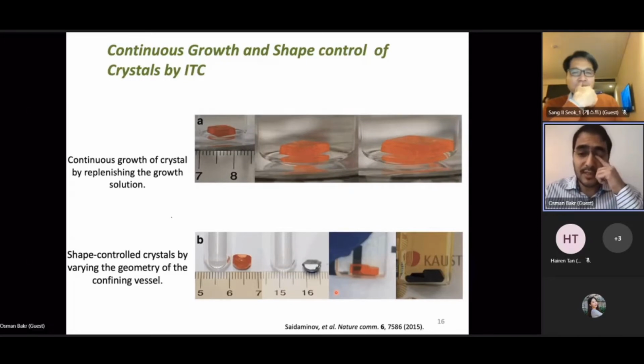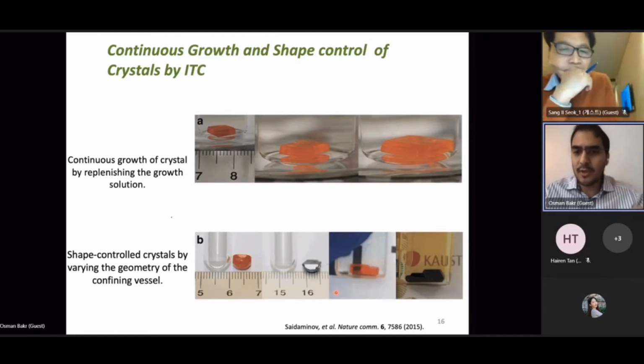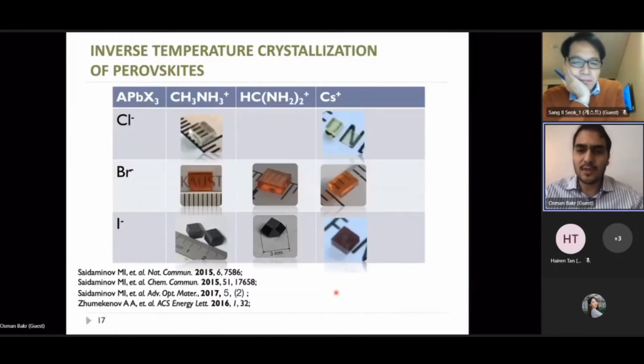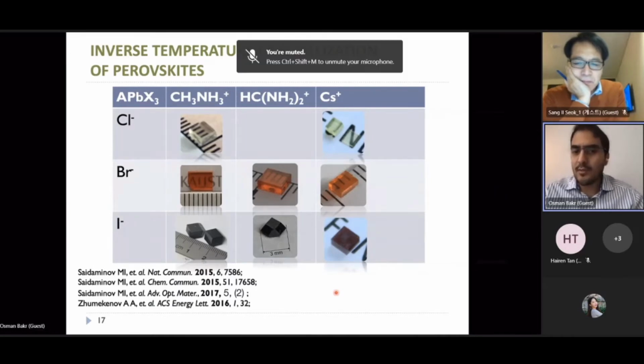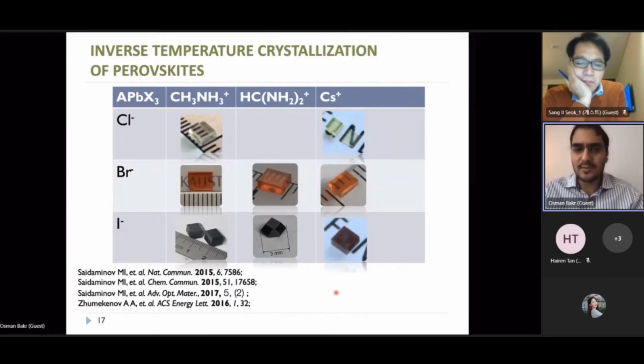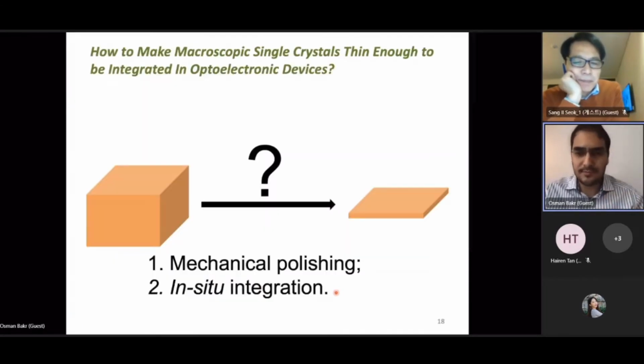And at the time, we also noticed that we could use this method to grow crystals into the shape of the vessel that we wished. We weren't sure what to do with it at the time, but I'll show you later why that is important. We could keep growing the crystal over and over again. And so this process can be used to grow crystals large and small. And we showed that so many perovskite materials fall under this inverse temperature crystallization approach. And it's applicable to a lot of different perovskites as long as you use the right coordinating solvent.